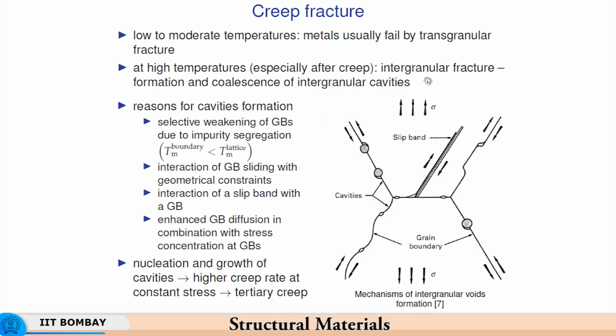And particularly if you take Nabarro-Herring creep, you will get failure irrespective of the fact that the stress might be low, and irrespective of the fact that the grain size could be small or big. The creep rate will be governed by the grain size, but the failure will always take place in an intergranular manner in case of a Nabarro-Herring type of creep.